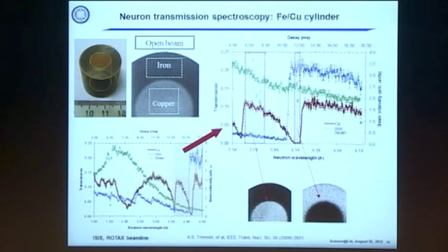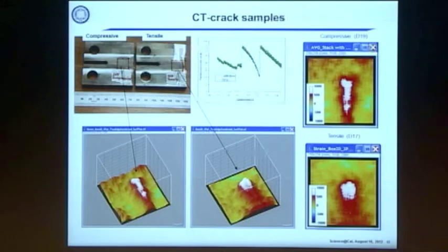but more important, you can measure the position of this Bragg edge, and from that position, you can tell the strain distribution within the sample. Because with our detectors, we're detecting time and position. Again, that's a unique thing, with high spatial resolution, and then we can tell in a particular pixel of our image what is the spectrum of transmission. And once we know the spectrum of transmission, we can recover the Bragg edge position. And from that, it's a little bit complicated maybe, but from that we can reconstruct the strain distribution.